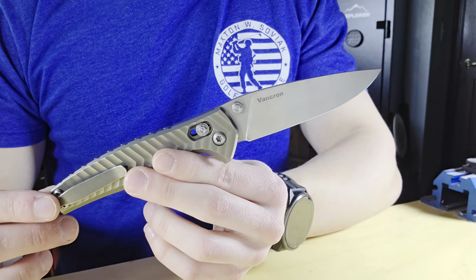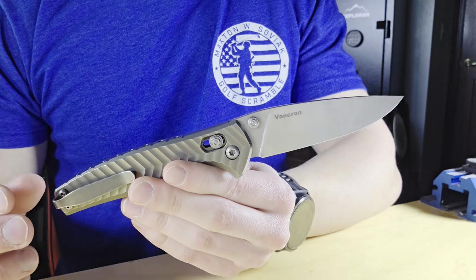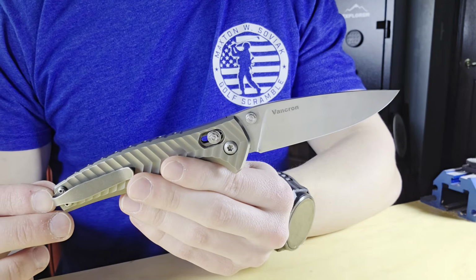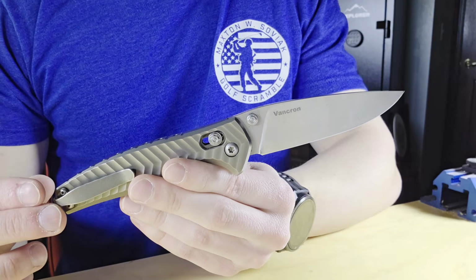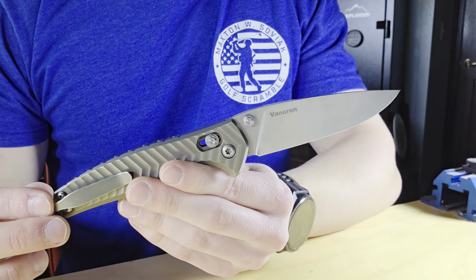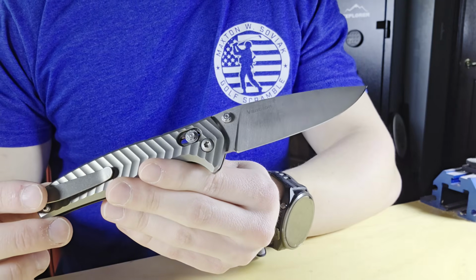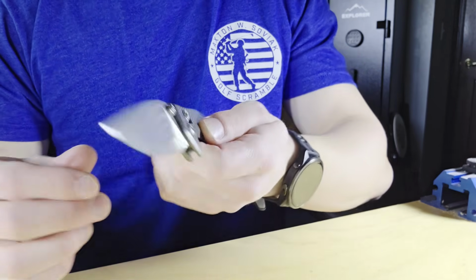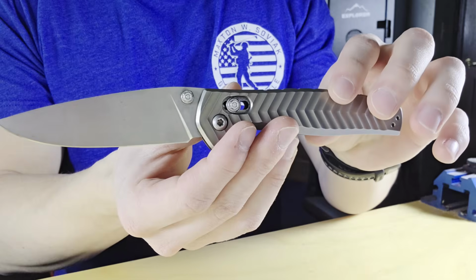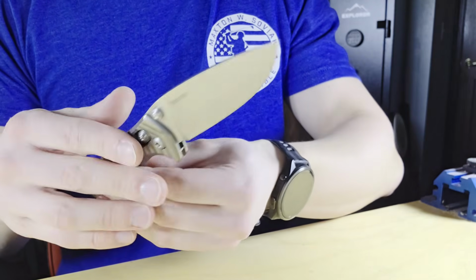Despite that nitrogen in the composition, it's not stainless. Nitrogen only helps boost the corrosion resistance when there's enough chromium in solution. So this is a nitrided tool steel. It is not stainless, and it actually does have a little bit of patina on it here and there. I'm not sure how well the camera will pick that up, but there is a little bit of patina on this.